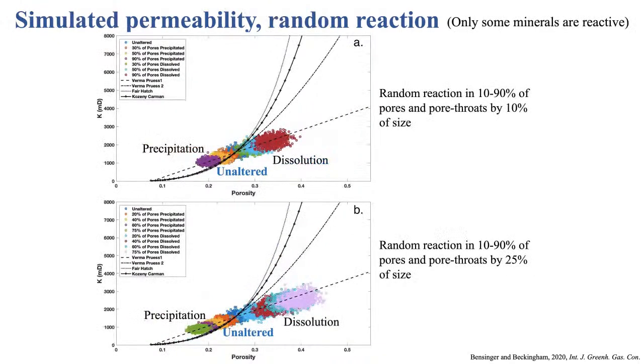Now if we look at randomly distributed reactions, so this corresponds to only some of the minerals being reactive in our system. We can see something similar to the uniform reactions where we have increases in porosity and permeability with dissolution and decreases with precipitation that are reflected pretty well with the Verma-Pruess equation.